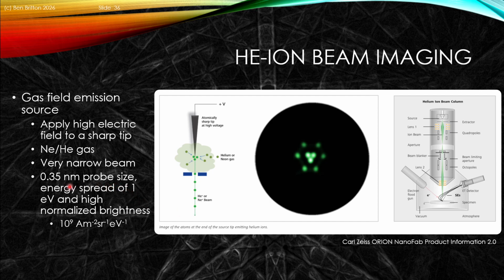We get a very tiny probe size, and it's very monochromated. It typically has a reasonable brightness for our system. There are some challenges in these cases. And this is found, for instance, in the Carl Zeiss Orion NanoFab product for this particular case. Again, the FIB itself, the helium ion beam system, has our source that's just changing to this type of source on the left. But it has relatively simple and similar electron optics, as well as detectors that are in the sample chamber.